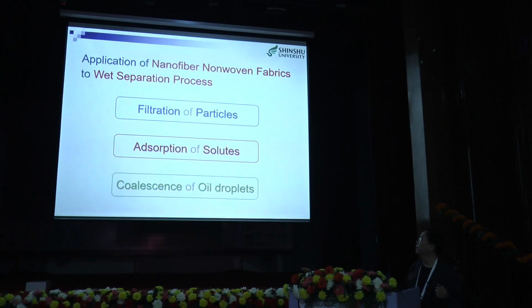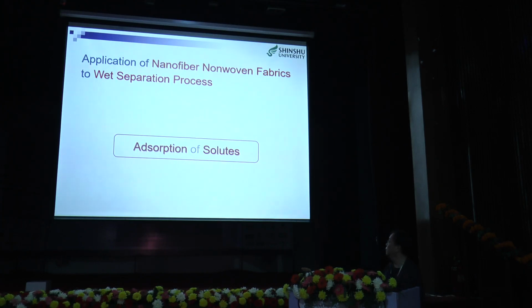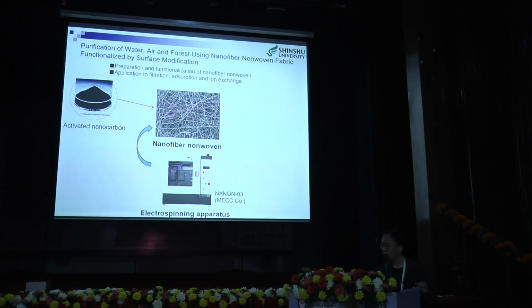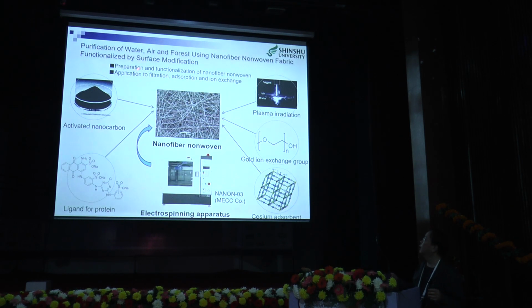My research field is wet separation processes such as filtration, adsorption, oil-water separation, and so on. I am challenging to apply the nanofiber non-woven fabric to wet separation processes. For example, adsorption of solutes. We prepare and functionalize the nanofiber non-woven fabric with various functional materials like this, and apply them to selective adsorption of some solutes, heavy metal ions, and protein.